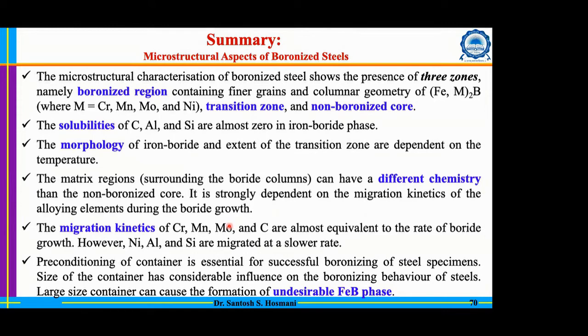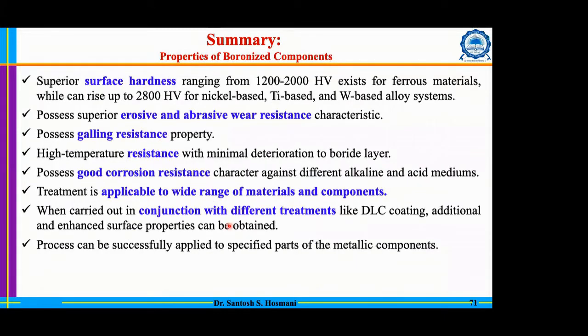So that is better to avoid that as much as possible. And then with respect to property, extremely good hardness you can get. Depending upon the proportion of ferrite and matrix, your hardness can be as low as 1200, even as high as 2000 HV. And even the non-ferrous material can also give you the borides there, and it can give you even further high hardness there. And superior erosion and abrasion wear resistance has been observed.